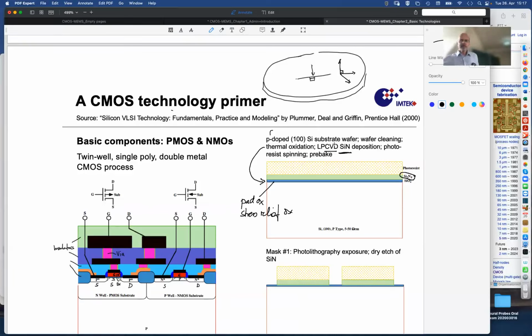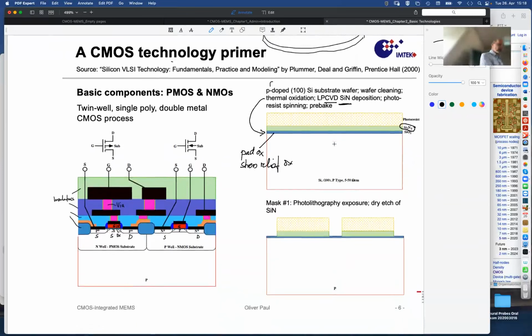And then we see a yellowish layer that symbolizes the photoresist that is spun on top of that wafer over the entire surface, and then pre-baked, and then in the next step exposed to an optical pattern. So the mask is put on top, or adjusted on top, and then there is some exposure with some lamp with some appropriate light frequency or light wavelength, light energy, and that after some further processes belonging to photolithography, so post-exposure bake and then etching of the photoresist.